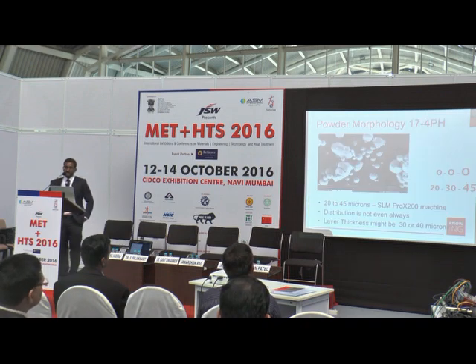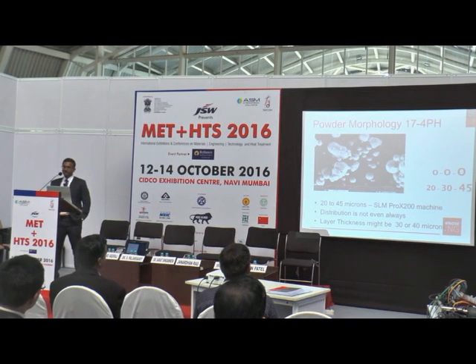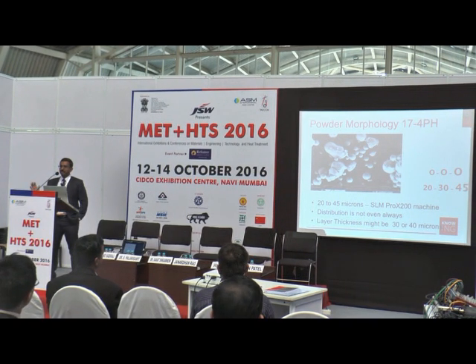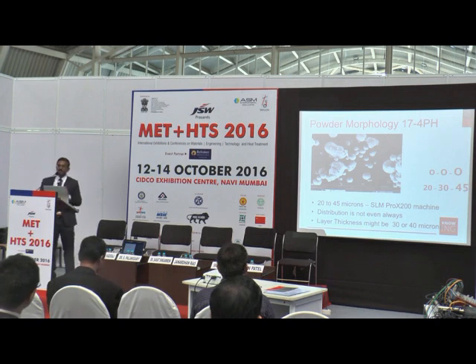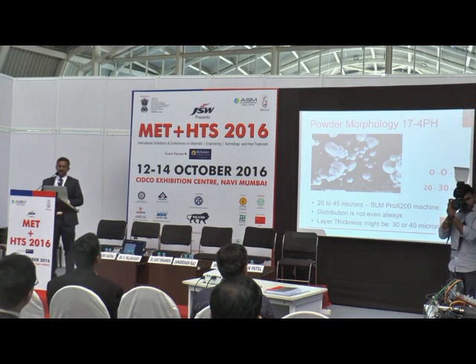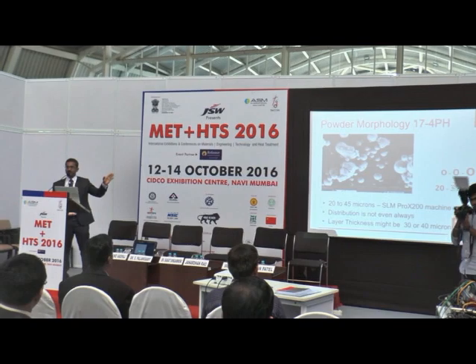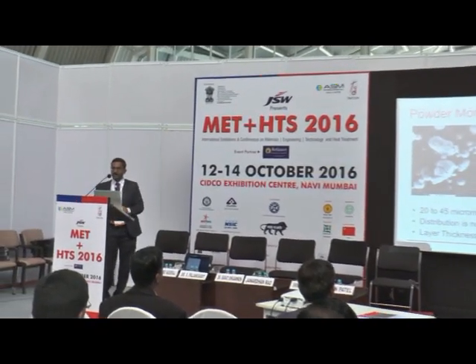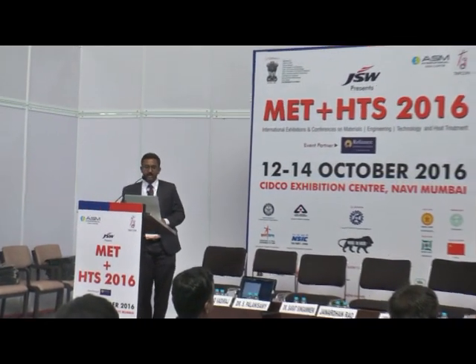When I talk about the powder morphology, in this particular case, I'm talking about 17-4 PH material. When we get a powder, it ranges from 20 to 45 microns, but it's not evenly distributed. That's the critical thing. I just try to show you different sizes, 20 microns, 30 microns, or 45 microns. That's how it might look.